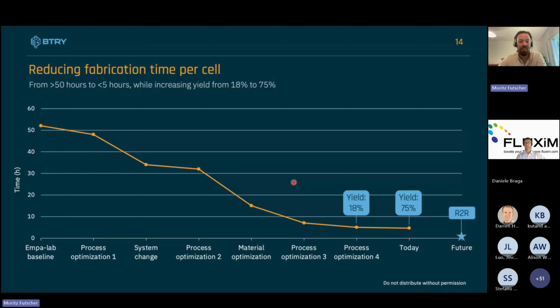At the same time, we needed to decrease the deposition time. So here you see what we were used to in research times. It took about 50 hours to fabricate one of these cells. And over time, both through optimization of processes, changing the processes to more industrial-sized, scalable processes, but also through the systems which we're using, we were able to decrease this to below 5 hours today, with a promise to go even much lower than that in the future, while simultaneously increasing the yield of the production. So these are really two key aspects which we did as a startup: increasing the area and decreasing the deposition time to have a higher output.